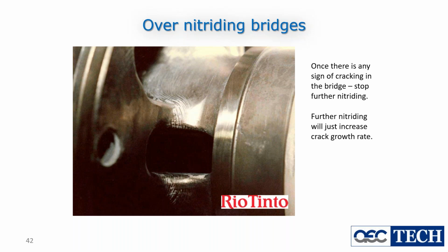Last thing from me on this. If you have a bridge die and you're regularly nitriding the bridge and the plate, once there is some cracking in the webs, stop nitriding the bridge. The reason being, when you nitride those cracks, nitrogen will get down in those cracks and it will make the crack tip more brittle and the crack will grow faster.